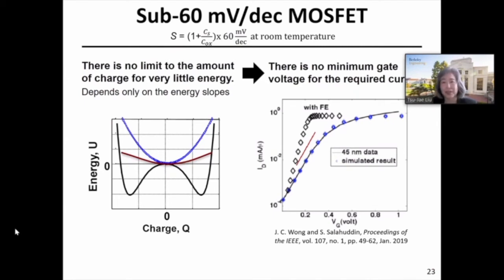And Professor Saif Salahuddin at Berkeley has been making really good experimental progress. The thickness of the gate dielectrics today is approaching 1 nanometer, and the ferroelectric that he adds is on the order of 1 nanometer. And that actually is good because you can get greater capacitive coupling between the gate and the channel region, but with a thicker material stack. And that actually helps to prevent leakage current between the gate and the channel, which can become a problem if the insulator is too thin.